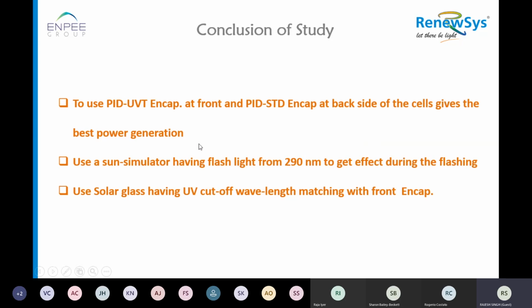And then this phenomena will be noticed only at the module level in your factory, only if you have a flasher starting from 290 nanometer flashlight, because otherwise this will not get detected by the cell, by your detector in the instrument, and you will not get the value, while the cell will not generate power because it is not getting the light. So light has to be there, which is 290 to 360 nanometer in your flasher.